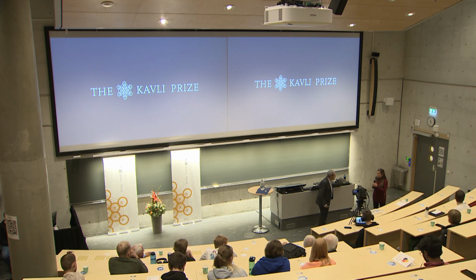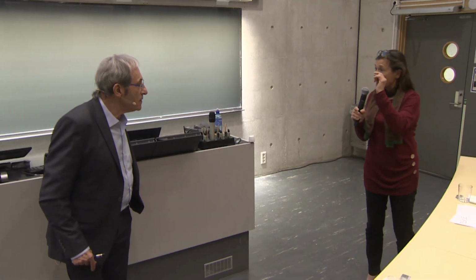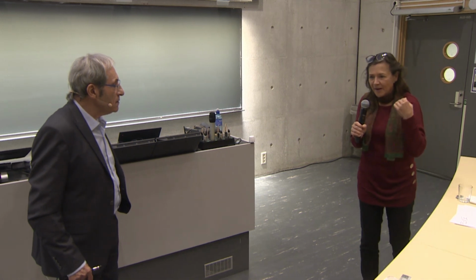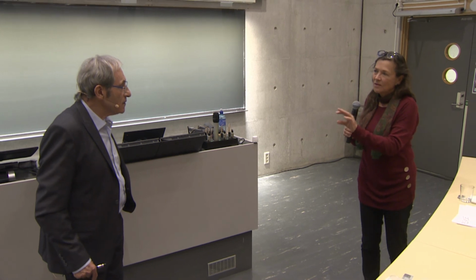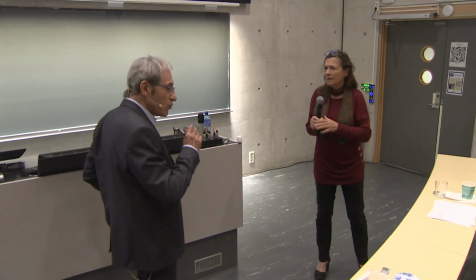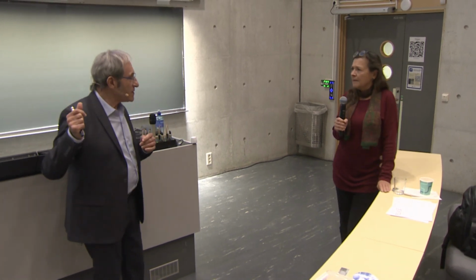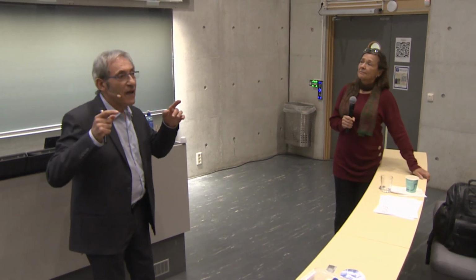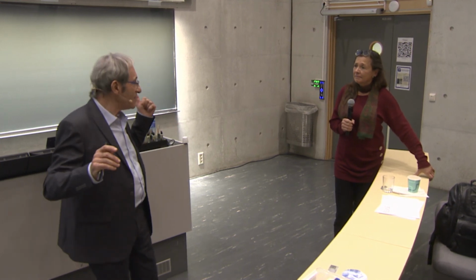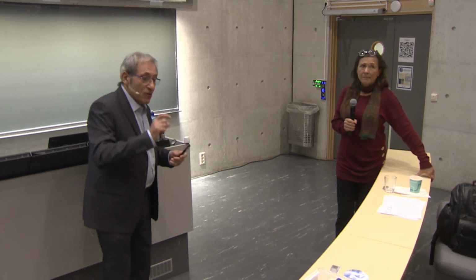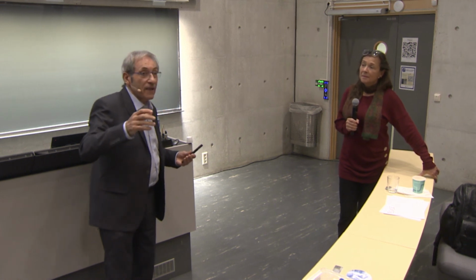So this Russian paper that you found, that's theory, that has the spatially separated charges, right? Considering how many people are working on single electron type devices, it's hard to believe that people haven't tried. They cited that? Yes, but they could prove that there is coupling, but they didn't find superconductivity. You see, the problem is also the exciton mechanism. There were many attempts. But the physicists work with physical methods, and with those methods, it was not possible to realize a system that has the predicted properties. We arrived at this indirectly, but we have the ingredients that came in. Actually, right from the beginning, I thought about superconductivity, but in a totally different way, not like this way. Also by accident. So we have the right system, the insulator with the right thickness.